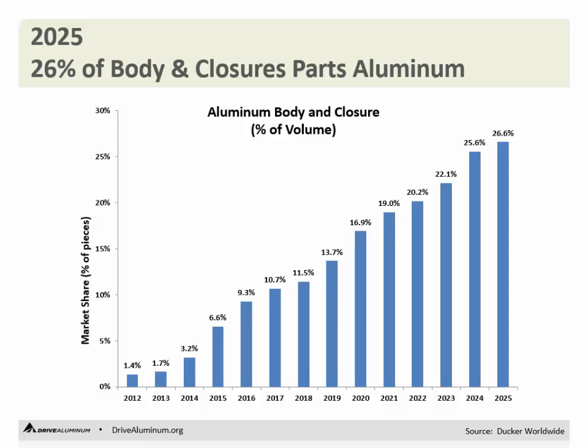That growth is fairly continuous, even going back to the 2012, 2013 timeframe. It's a steady growth, which includes, in 2015, the large step of the F-150. But if we look at the total trend over a long period of time, there's a very steady growth curve expected for body and closure volume in aluminum as a percent of the parts in the marketplace.